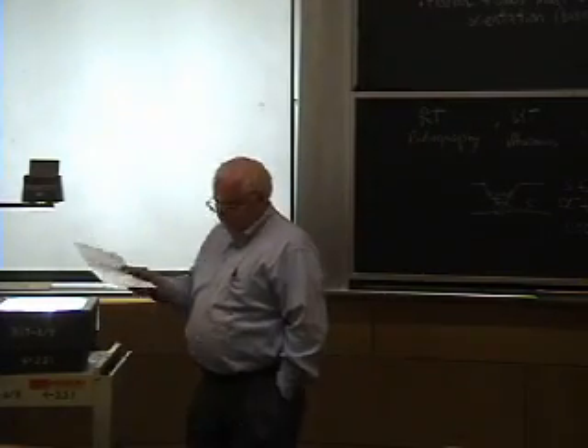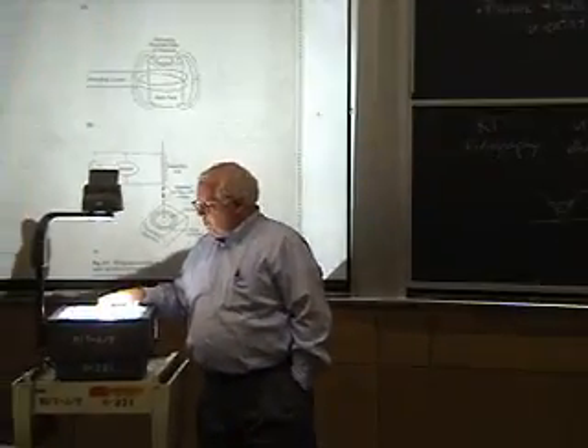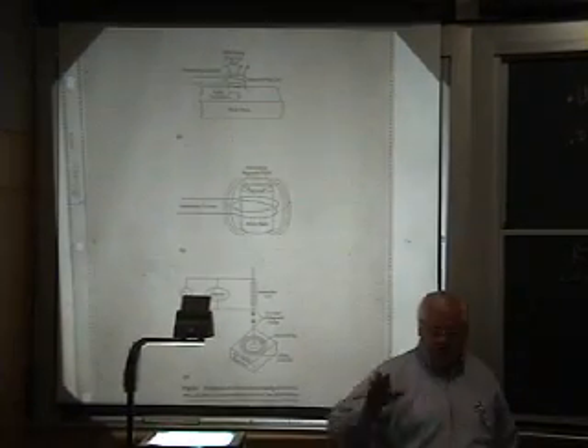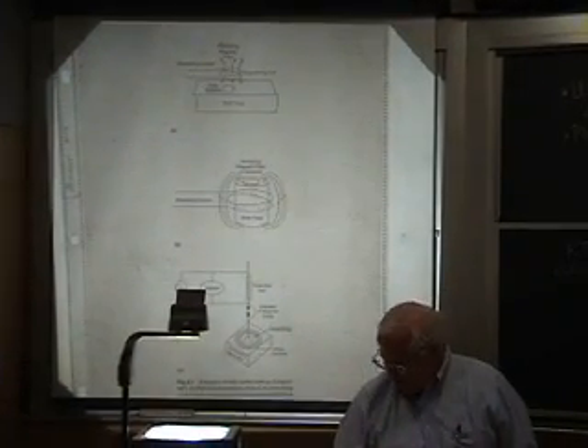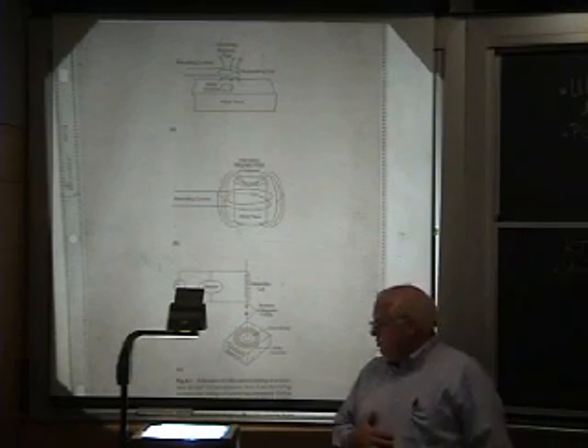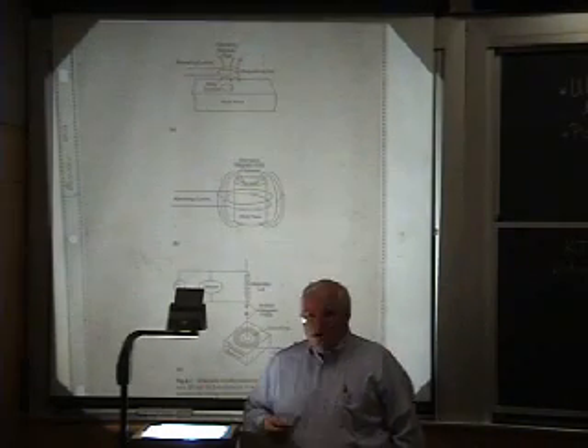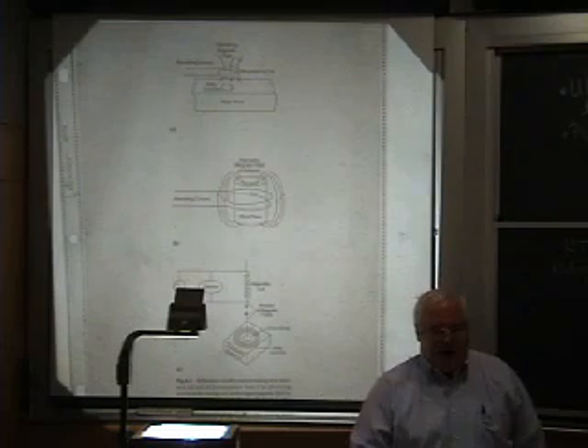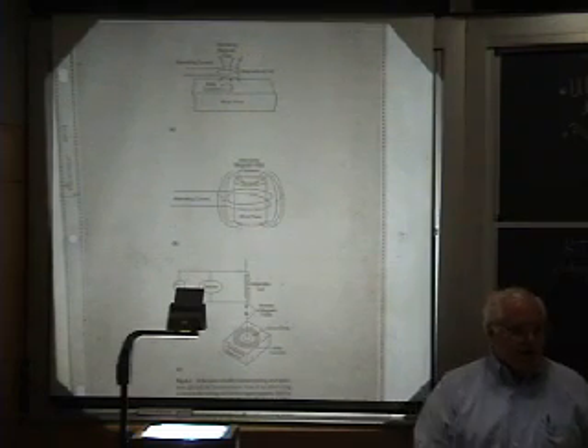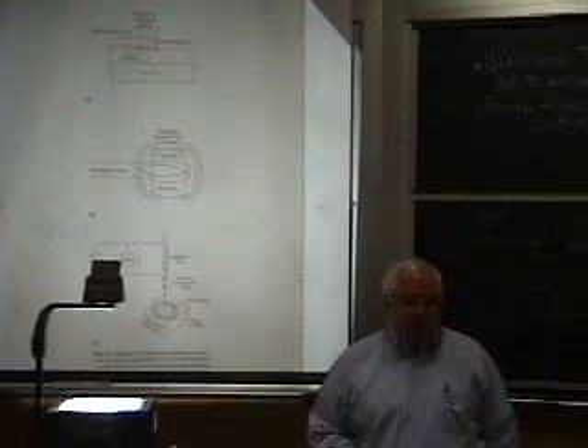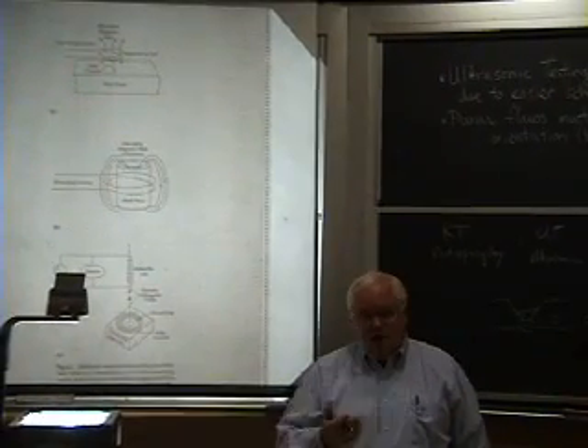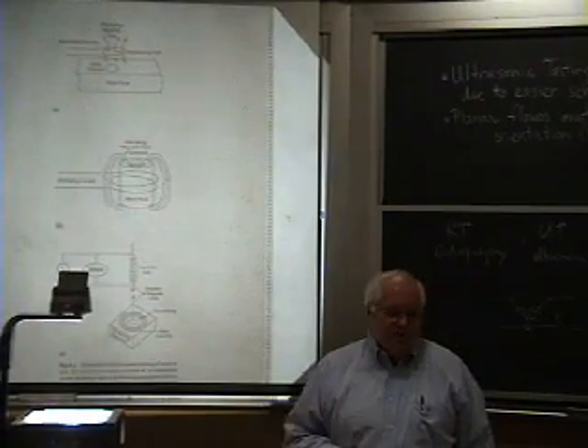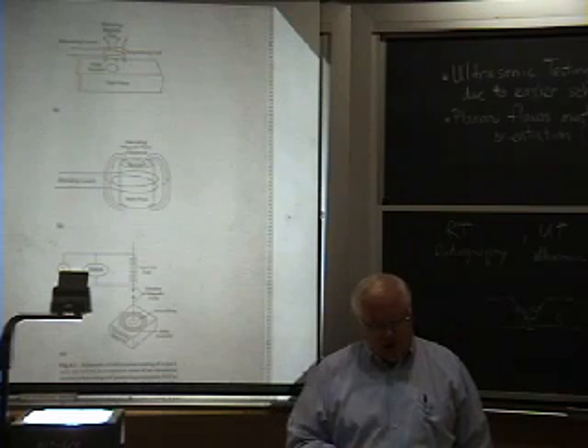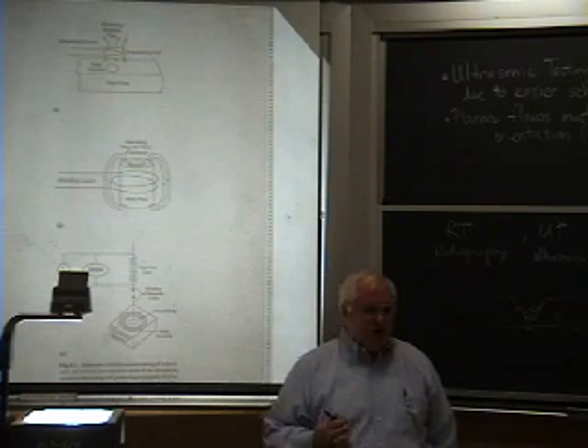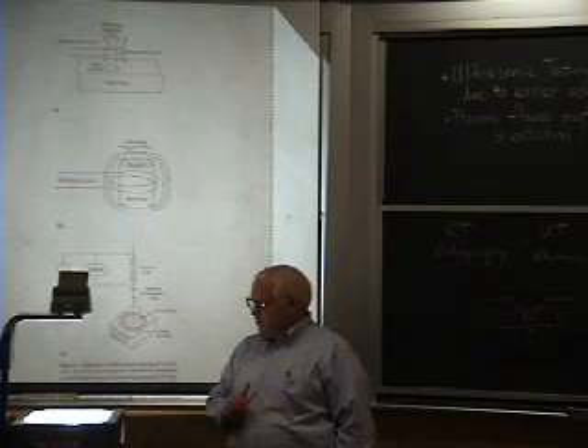The last inspection technique, not the last of all possible ones, there are literally dozens, if not hundreds, of non-destructive testing techniques. But another common one that's used is eddy current. And if you go to Radio Shack and you buy yourself a magnetic detector to take down to the beach to see if you can find some old beer cans or something, except they don't make steel beer cans anymore. The magnetic detectors are best on ferromagnetic material, but eddy current works even on anything that's conductive. So it should pick up aluminum and stainless steel and others. It just doesn't have as great a sensitivity.